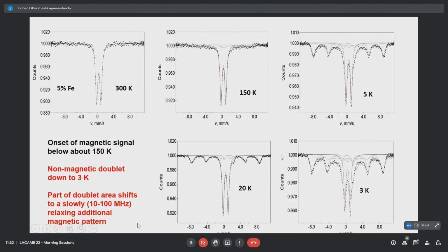And that's actually what we see also in the muons. In the muons for this compound, we see an onset of the slowing down of correlations below about 150 Kelvin. That's exactly seen here also. So what does it mean? We have here also the possibility, by introducing iron as a spectator, to monitor the slowing down of the spins in the matrix. So the spin fluctuations are of the order of 10 to 100 megahertz. That's very similar to what we see with the muons.